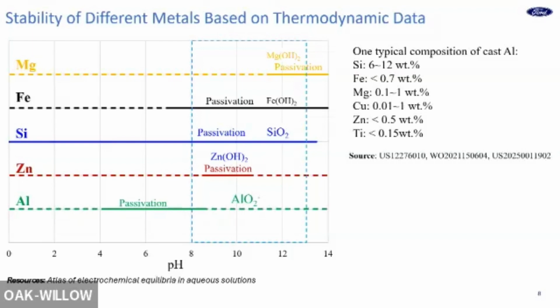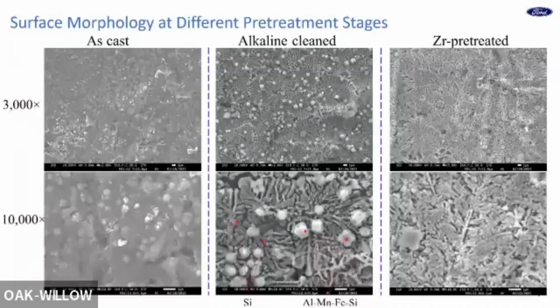thermodynamic data, but let's see what happened on the real cast aluminum dipped in the commercial products. This is the surface morphology of the cast aluminum at different stages: at the cast condition, after alkaline cleaning, and after zirconium pretreatment, at 2 different magnifications, 3,000 and 10,000. You can see at the cast condition, it's pretty smooth. You may see some small particles over here, but after the alkaline cleaning, the surface becomes very rough and actually